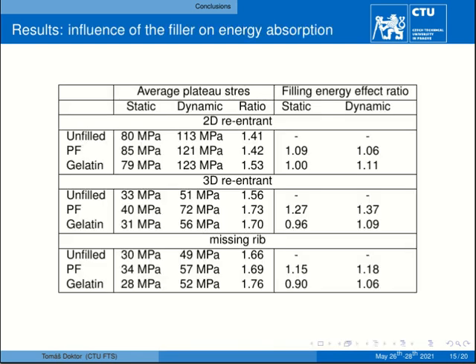In this table, the ratio between unfilled and filled specimens in terms of increase of strain energy density is presented for all of the types of the auxetic structure, and you can see that while at static condition the increase was not that significant, and even for the ordnance gelatin a decrease of strain energy density versus mass was observed. In the dynamic condition, all types of auxetics with both types of filling show increased strain energy absorption properties.